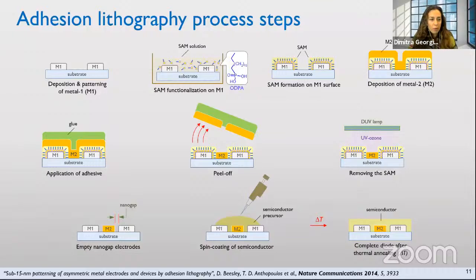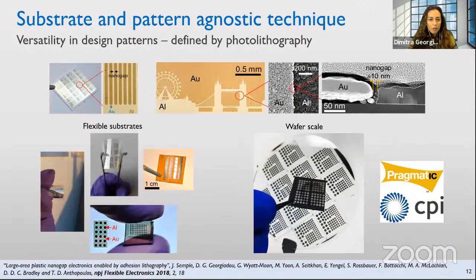So we end up with an empty nanogap electrode, and then we can deposit from solution the precursor of our semiconductor, and after some annealing, we have the film on top of the pre-patterned electrodes. From what I showed so far, you can tell by yourselves that this is a substrate and pattern agnostic technique. There is a huge versatility in design patterns we can use because they are defined by photolithography. And that's why we can do a lot of scaling studies with these electrodes.